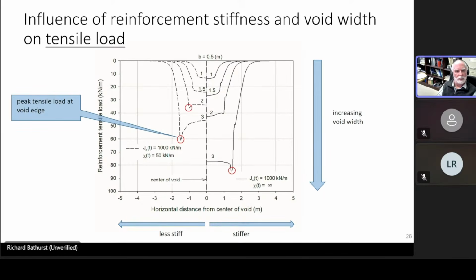But again, the tensile load is a function of the stiffness of the reinforcement and the void width. So here, again, on the right-hand side, you can see that the loads are highest for the stiffer reinforcement, which is not unexpected because we all know that in structures, if you have a stiff element, it tends to attract the load. And this is the same thing that happens in our problem.